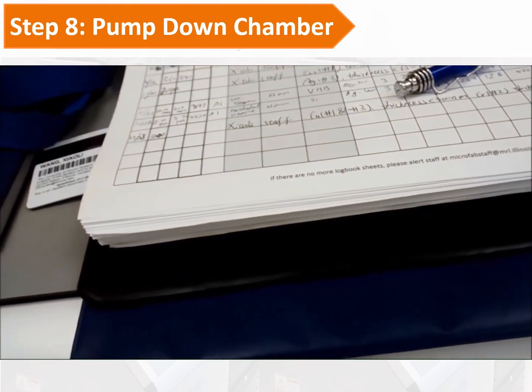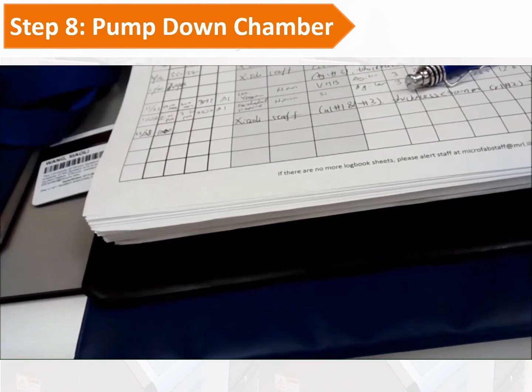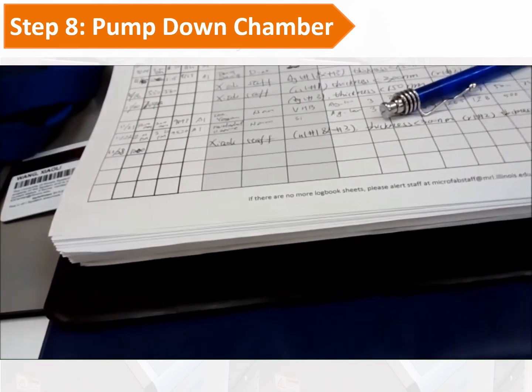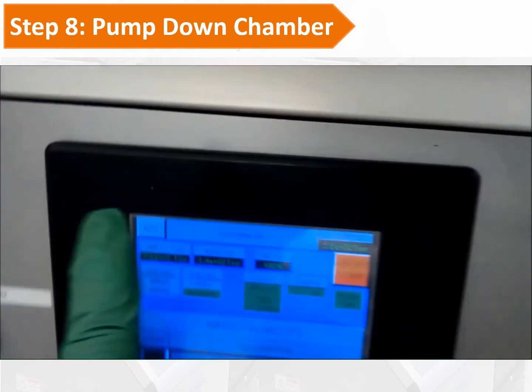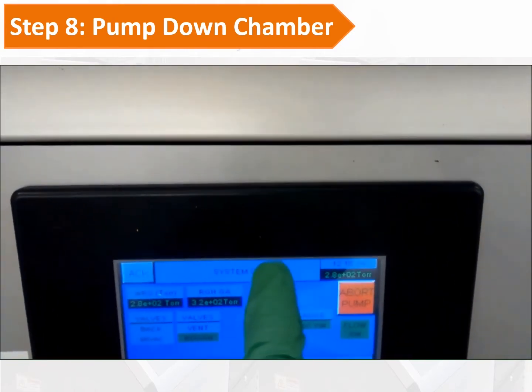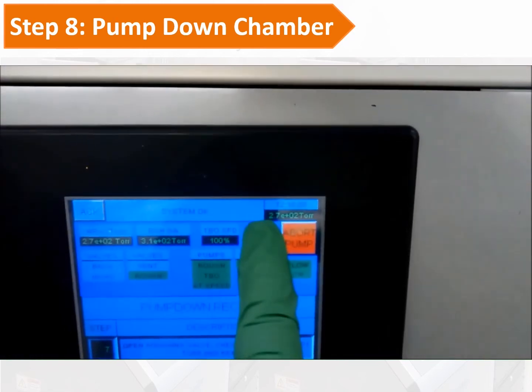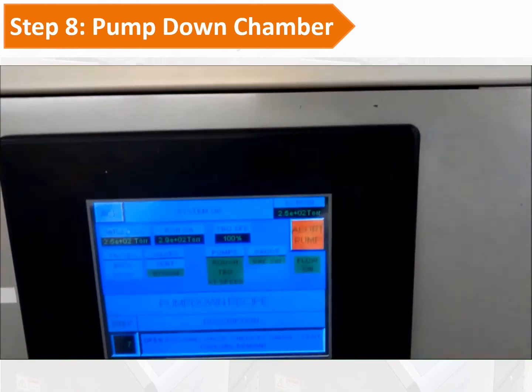Just double check, make sure the chamber is under vacuum before you leave. If you find any error, or if the pressure does not change, please report to staff and leave a note near the system.